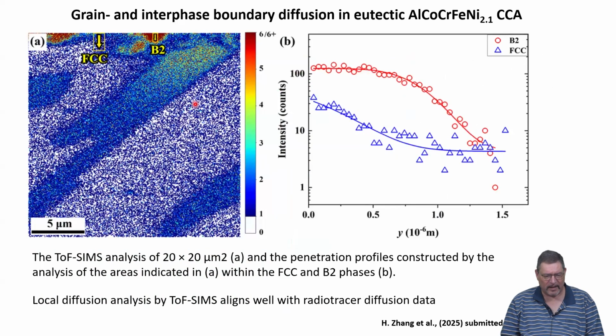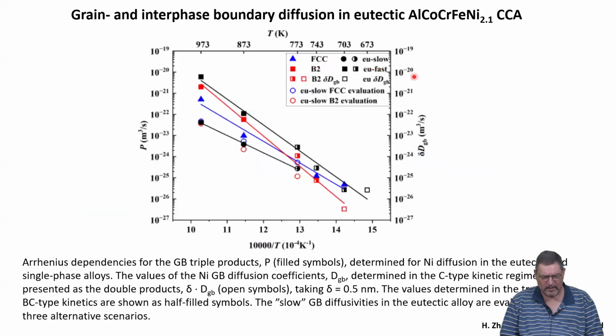We can also analyze from this time of flight secondary ion mass spectroscopy measurements the diffusion profile, the penetration profile, to analyze diffusion coefficients. As I said, accuracy will not be so high as compared to the radio tracer method, but still it's good enough. So we can obtain the penetration profile as a function of depth and then do the normal analysis that we have talked about over the past lectures, and then basically get a confirmation that the diffusivity values which we obtain are rather similar to what we get from the radio tracer method.